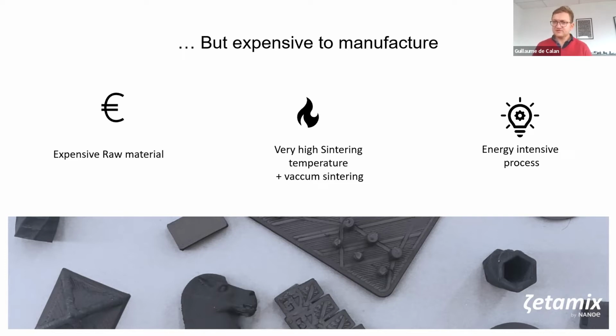So it is the reason why silicon carbide is actually more like a last resort material. We print in silicon carbide when other materials won't be good enough. Typically, for us, the low-cost version of silicon carbide would be aluminum oxide. It's a bit similar in properties - it's lightweight, very hard, relatively chemical resistant. But in some cases, alumina won't be strong enough, won't be light enough, won't be corrosion resistant enough, and that's where we will go for silicon carbide.